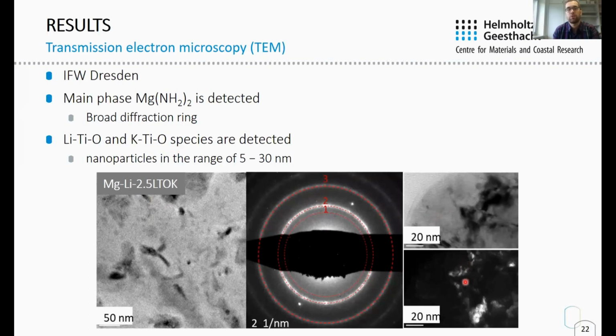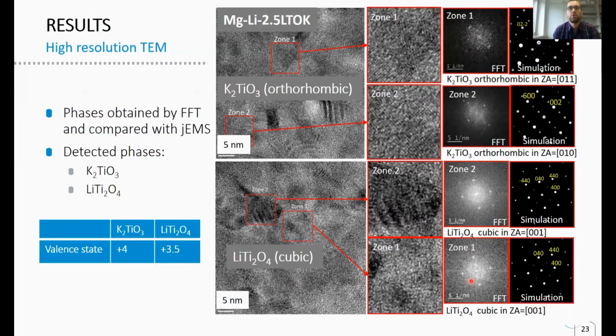In order to verify such nanoparticles, high-resolution TEM observations were performed on the same sample. With high-resolution TEM, nanoparticles of potassium titanium oxide are found in two zones as seen in this image. And below, we found lithium titanium oxide nanoparticles. Titanium has an oxidation state of +4 in K2TiO3, and 3.5 in lithium titanate. The presence of these compounds leads to an effective valence state between 3.5 and 4, which is in agreement with the results obtained from X-ray absorption spectroscopy.